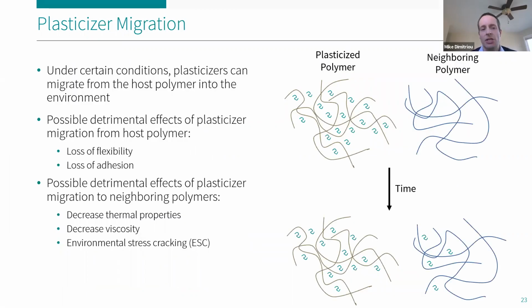So back to plasticizer migration. As a formulator engineer, when you put a plasticizer in a polymer, what you essentially want it to do is stay in that polymer. You want it to stay in place, and you want it to keep the material as flexible as it was the day it came off the production line. Unfortunately, that is not always the case. Plasticizers are known to migrate when a material containing plasticizer is in contact with a neighboring polymer. In the simple depiction on the right, the polymer on the left is formulated to contain some amount of plasticizer. And when put in contact or close to a neighboring polymer, over time, some of that plasticizer migrates into the neighboring polymer.